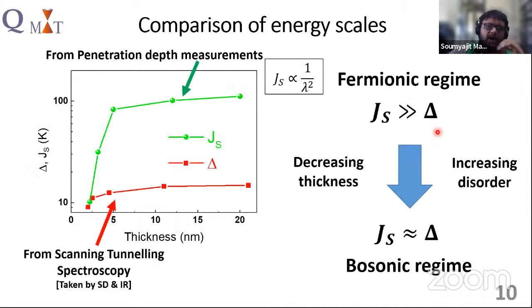So now to conclude, I will just compare two energy scales from two measurements. One is the JS, which is the superfluid stiffness from the penetration depth measurements, and another is the superconducting gap from the scanning tunneling spectroscopy. So as you can see, at the higher thickness samples, the JS is much greater than the delta, which is also the case for the conventional superconductor. That means the phase is rigid in the superconducting state. But as we go to the lower thickness sample, the JS becomes comparable to the superconducting gap.